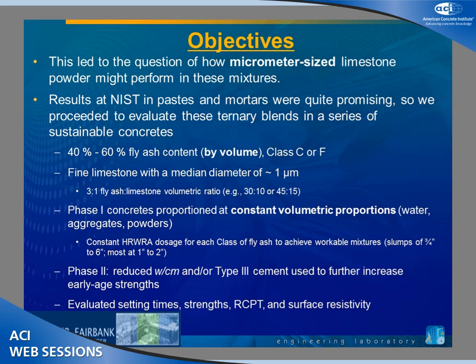Obviously, the more surface area you're supplying, you might expect to see more benefits or more effect. And so we were working in this study for the concrete with the 1 micron material. And we selected from previous work, we knew that the ratio we wanted to use volumetrically was about 3 to 1. So for our 40% replacement, 30% fly ash, 10% limestone, 60% replacement, 45% fly ash, 15% limestone.